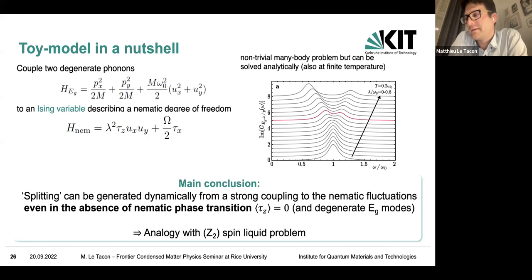No, that's correct. This is something we had a bit overlooked, but we're on it. So here's the thing. When you take the system and start from the tetragonal phase and cool it down, a few things happen. The first thing we see is the broadening of this EG mode. That EG mode couples to something that is appearing there, and that thing gently develops alongside the I-CDW correlations.